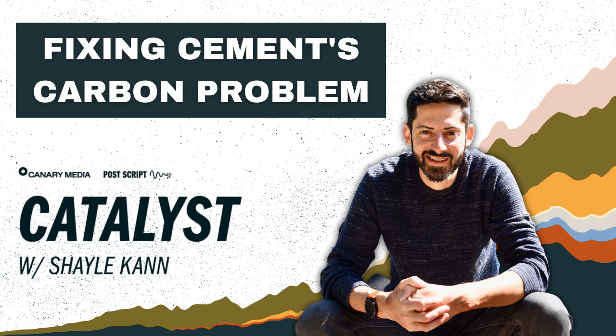Yeah, so the benefit is that it's lower in CO2. Obviously we're getting rid of that half of cement CO2 emission that's from the fossil fuel. And also we can get rid of the other half of cement CO2 emission, which is from the minerals or the limestone that's used. What's cool about Sublime's process is that it's not a thermal decomposition of the calcium carbonate. Remember, calcium carbonate decomposes in a kiln and the CO2 escapes as a gas, and then you have a solid calcium oxide. Sublime goes about this in a different way.